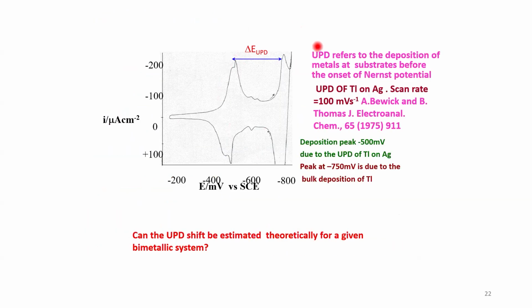You can see this is called the under potential shift, thallium on silver. Normally, this peak would not have occurred in the bulk deposition. Here it is under potential deposition. So this is called the shift in the under potential deposition. Very long back, in 1975, they did this. The theory is still not yet ready.